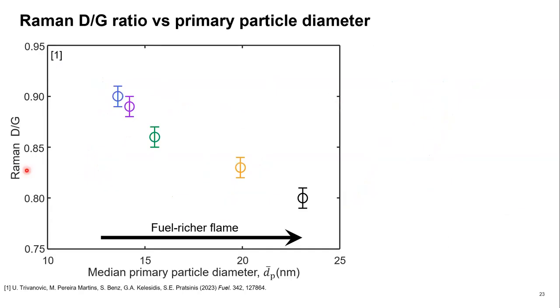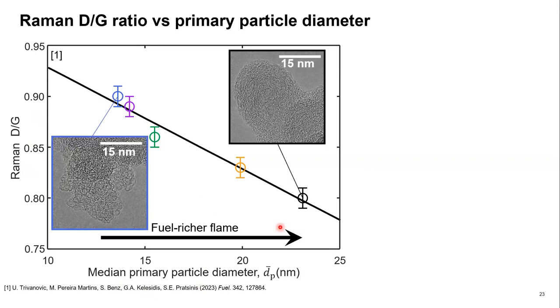If we plot this Raman D to G ratio as a function of the median primary particle diameter, we see that there is a very clear trend between the degree of graphitization and the size of the particles. Qualitatively, we can also see this in the microscopy. For the smaller particles, there is a certain amount of disorder that you can see from the shape within this TEM image. And when we go to the larger particles, visually, you can see that they are much more ordered.